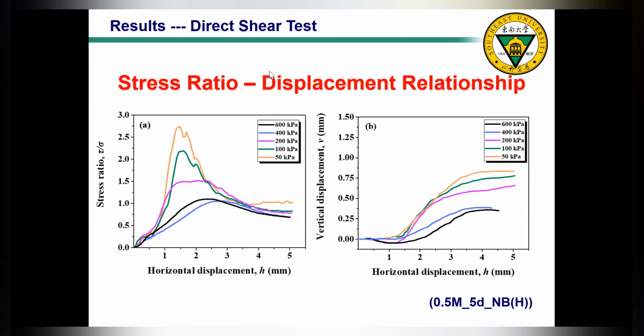Next, let's see the direct shear test results. Firstly, the stress ratio displacement relationship. Here I just pick 1 representative case. With the increase in the normal stress, the peak stress ratio drops, and the displacement corresponding to the peak also increases. If we look at the vertical displacement versus horizontal displacement relationship, at low normal stress, 50 kPa, the soil is quite dilative. However, when the normal stress is elevated to 600 kPa, the dilation of the soil is suppressed and it becomes more contractive. So that's the general shear behavior during the direct shear test for the biocemented case.